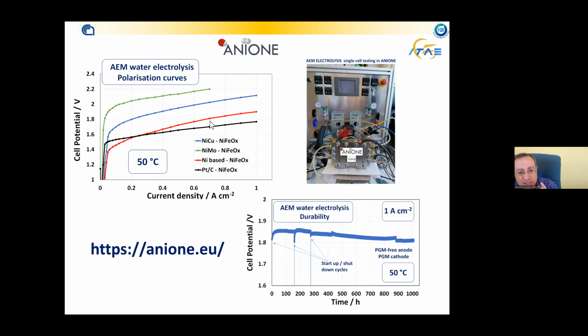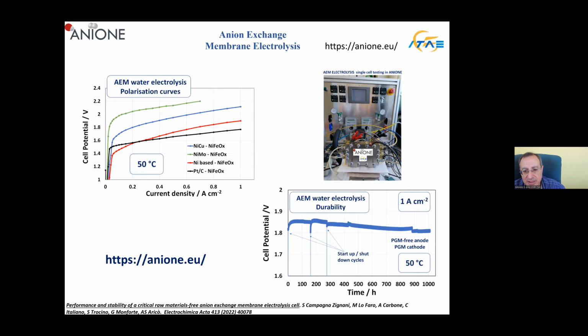But still, what I want to show is that in the case of AEM electrolysis, using non-critical raw materials like nickel and nickel iron oxide, we can achieve good efficiency and good durability. In this case, nice durability, because we have a decrease of cell voltage with time, meaning an increase of efficiency. This is a small prototype, 100 square centimeters. Of course, this is the new frontier in electrolysis technology, but 100 square centimeters is nice to really study the performance.